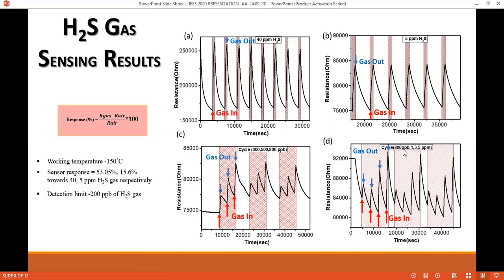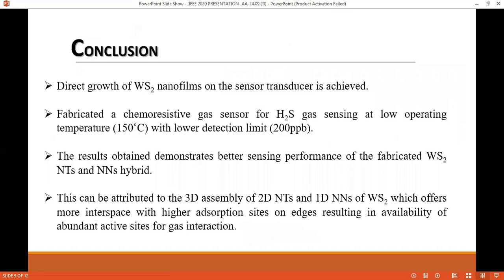Exposing the sensor to lower concentrations of H2S gas revealed the gas detection limit of the fabricated sensor is 200 ppb at 150 degrees Celsius. From the results, it is quite evident that there is an increase in response with each increment in analyte concentration.